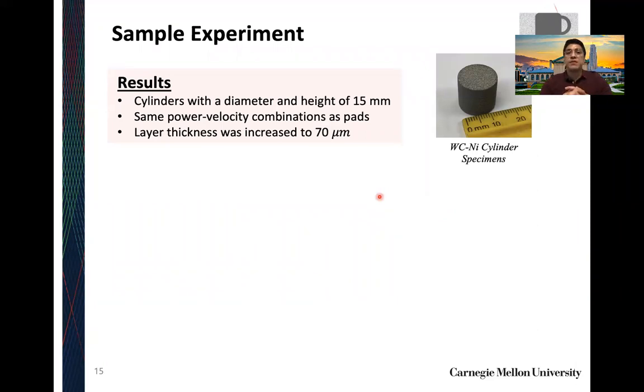Like I said, the same power velocity combinations were used, but this time we unfortunately had to increase our layer thickness to 70 microns. The reason for that being with the 50 micron layer thickness, as we started getting to higher heights or more layers, we started getting thermal buildup, which was causing thermal warping in the part itself. And that's simply due to the fact that the heat can't be dissipated fast enough and there's too much heat being concentrated within the part itself.